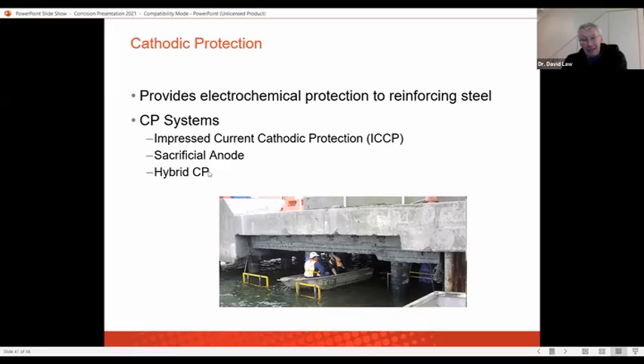And there is a new system, a hybrid CP, that's been coming in the last 5 years or so, that effectively uses impressed current, or applies a current, a very high current for a short period of time to get the steel passivated, but then protects it over the longer term with a sacrificial anode, because once it's passive and you've got that passivation, you've got that residual protection that can just be maintained by your sacrificial anode.